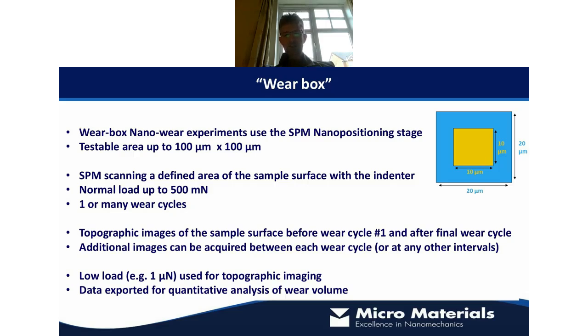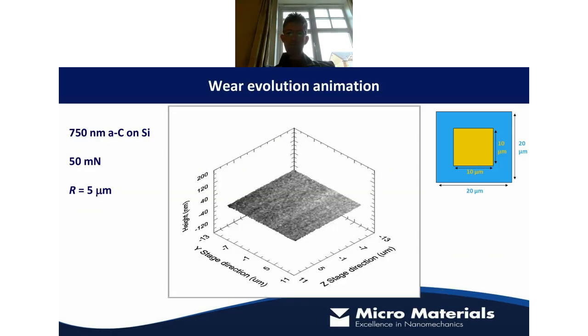And typically with the topographic cycles, we're keeping those loads very low, typically of the order of 1 micronewton. And then we can export the data for quantitative analysis of wear volumes. This is some work that Adrian did, in this case looking at a 750 nm thick amorphous carbon thin film, with a spheroconical probe, 5 micron in radius, and he just did some repeat tests in the central region at 50 millinewtons.